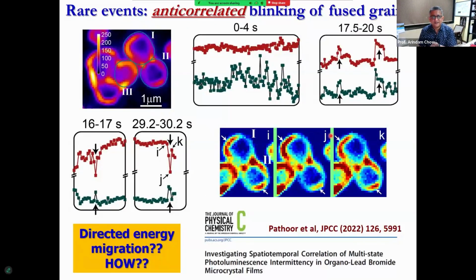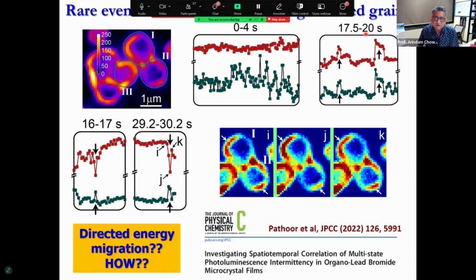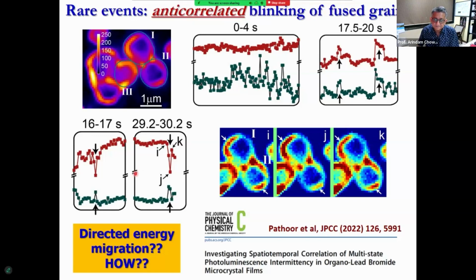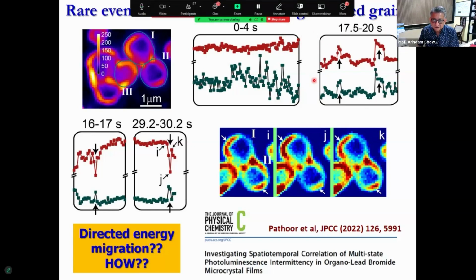Now, there are more weird events that happen, which although we have published the data, maybe for people to see, so that they can give us some hints of what may be happening, are these strange anti-correlated behaviors. If you look at these fused grains, there are 1, 2, 3, 4, 5. I want you to focus on 1, 2, and 3 here. And if you look at 1 and 2, that's what's plotted here. You can see from 0 to 4 seconds, there is no correlation. In between 17.5 and 20 seconds, there's clear correlation between the grains. So this is uncorrelated, and on the right is positively correlated.